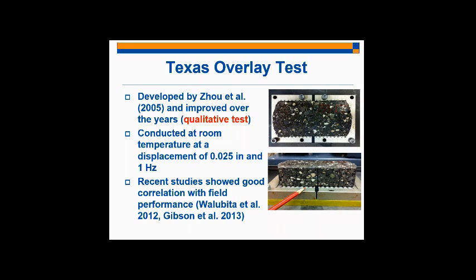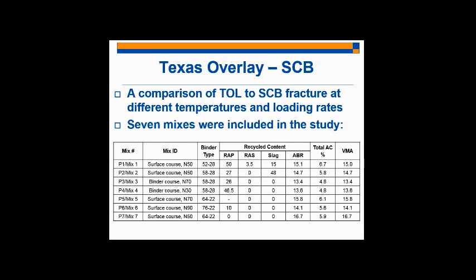And recent studies show that there's very good correlation between the Texas overlay test and field performance. And so what we did is we tested our mixtures under the Texas overlay with the help of IDOT, and we've also tested them under the SCB. And so there are seven primary mixtures included in the study, ranging from 0% RAS to 3.5% RAS, from 0% RAP to 50% RAP, and so very different mixtures.